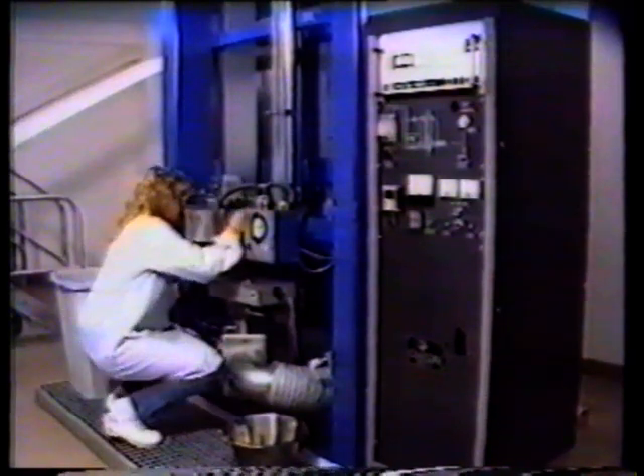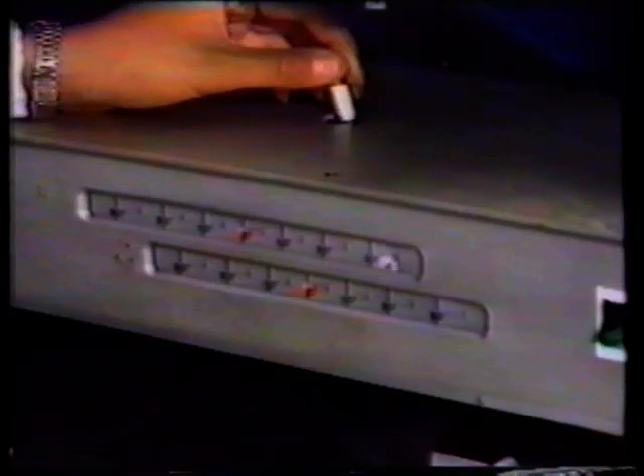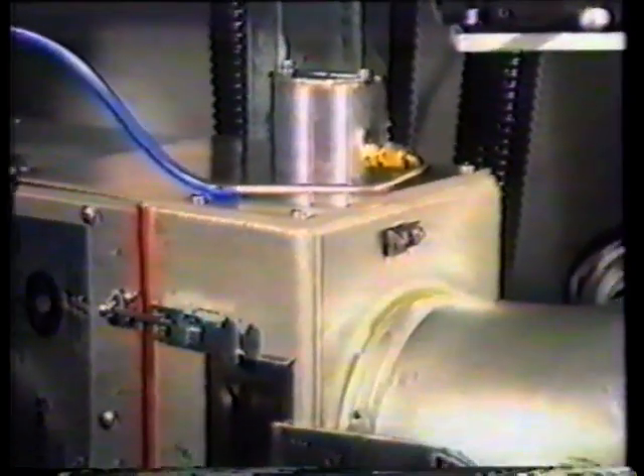The fiber is threaded through a coating cup where a layer of soft acrylate is applied to protect it. A layer of harder acrylate is then applied over the soft inner layer, making the fiber more durable. To check that the acrylate is being applied concentrically about the fiber, a beam of laser light is shown through the fiber, and the forward scattering pattern, which should deflect symmetrically, is observed. The coated fiber is irradiated with UV light to cure the acrylate layers.